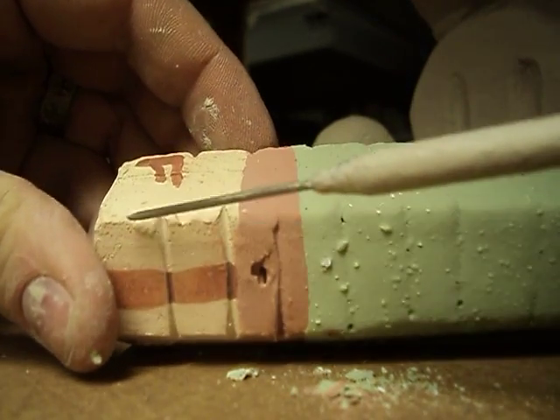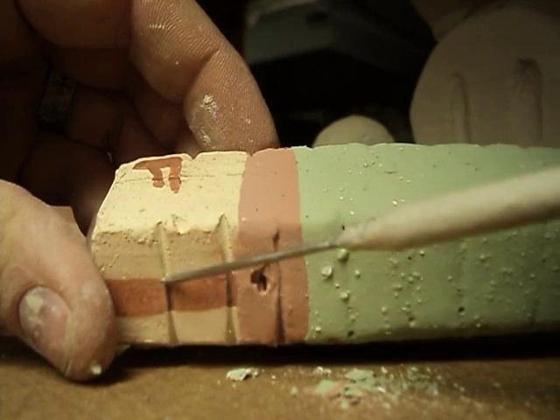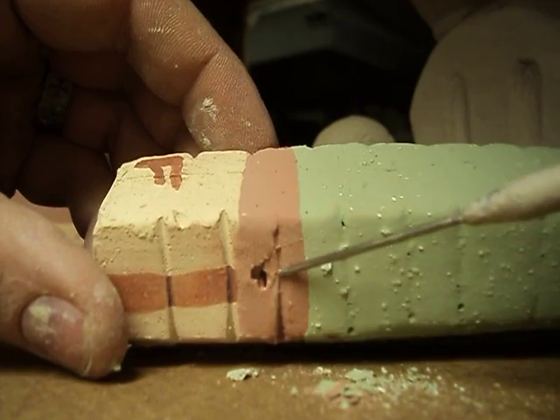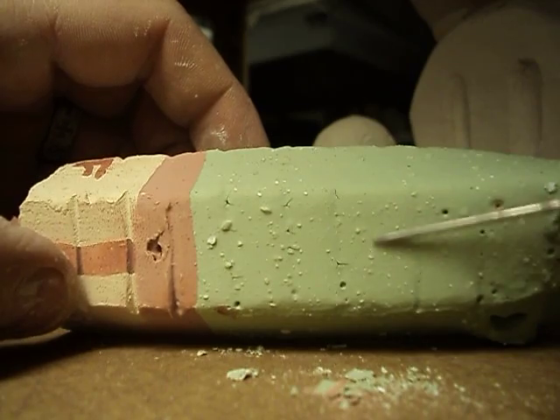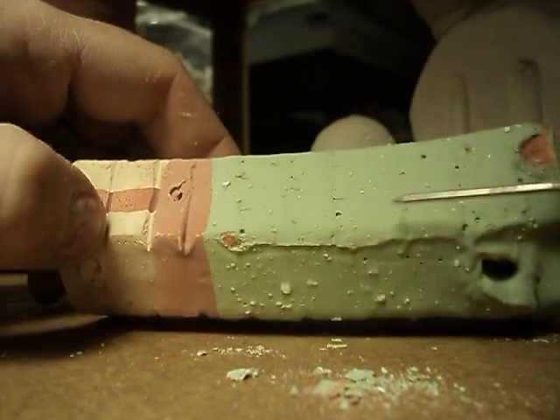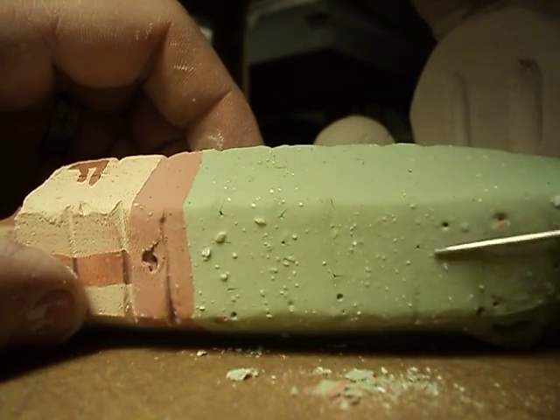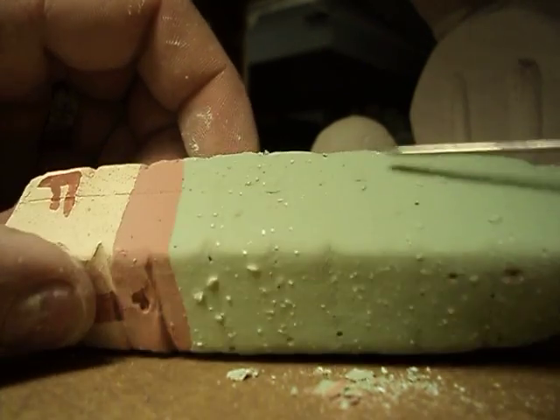The other thing I can tell you is to look at the detail. Here you can see all this detail in the test tile — these deep grooves. As I go over one dip, that starts to disappear, it's muted a little bit. Then for the second dip you can see it's mostly covering, and you can see little particles in here from where it wasn't quite mixed enough. Probably could have run that through a ball mill, but this glaze is pretty reliable without doing that.